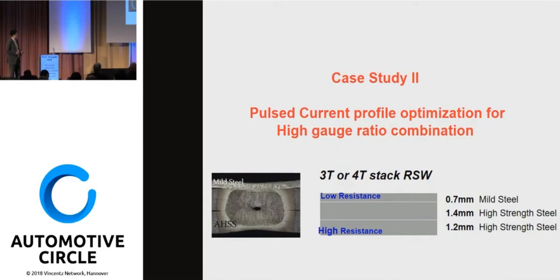Pulse current profile optimization for a high gauge ratio combination, 3-sheet high strength steel with a very mild steel. As ArcelorMittal explained, yes, they are right. Mild steel has a very low resistance, while high strength steel has a high resistance, which means that mild steel, because of its low resistance, needs a high current. But this high current will be very detrimental for the high strength steels. It will cause instant splash. So you can see here there is a conflict: mild steel requires the high current, but high strength steel doesn't need a high current.